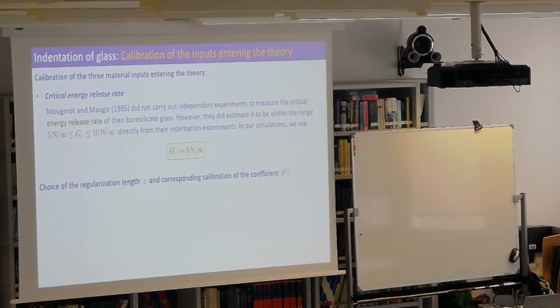Now, choice of the regularization length and the corresponding calibration of the coefficient delta epsilon. So remember that we have a delta epsilon in this driving force that needs to be calibrated. Once you have all the data, and once you choose an epsilon, you can choose whatever you want, sufficiently small, right? Choose an epsilon, then you need to calibrate delta epsilon. And the calibration is the same thing I told you before, right? Make sure that you agree with Griffith. If you change epsilon, you need to change the delta epsilon, right? You need to calibrate for all epsilon that you use.